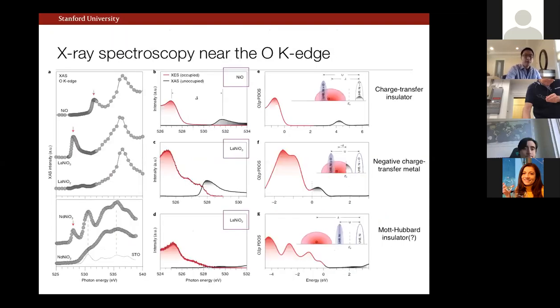So how can we see this? Sorry, this is a bit of a busy view graph. Let me just talk through a few of the key points. Let's first just simply look at the XAS spectra of the oxygen K edge. What you can see here is for nickel oxide, so the d8 configuration nickel, you see this strong pre-peak feature, right? And similarly for lanthanum nickel O3. This is well documented in the prior studies in the literature. But when we go to the infinite layer version of this series, you see almost no pre-peak amplitude, okay?